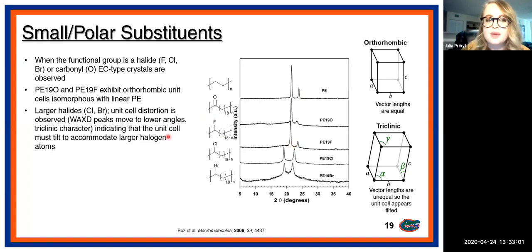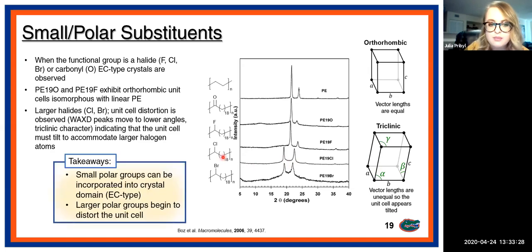And once we incorporate larger halides like chlorine and bromine, the scattering peaks go to lower angles, which means that the unit cell is having to increase in dimension in order to accommodate the larger halogen species. So these are still extended chain secondary structures, but the unit cell is having to tilt into more triclinic type of character to accommodate the larger atoms. So the takeaway from this work is that small polar groups can still be incorporated into the crystal domain, but larger polar groups begin to distort the unit cell.